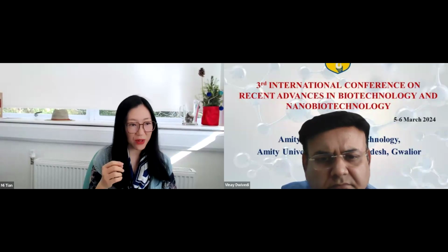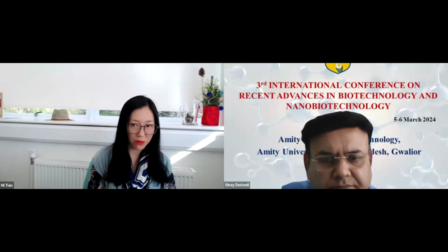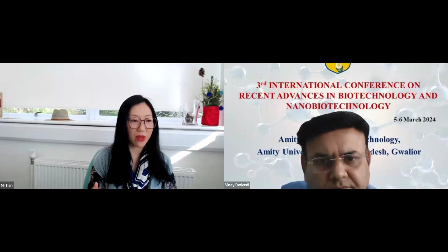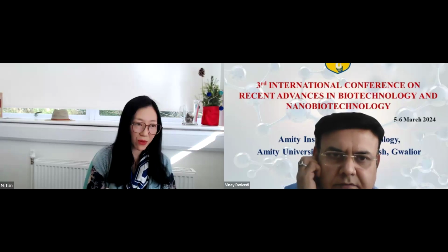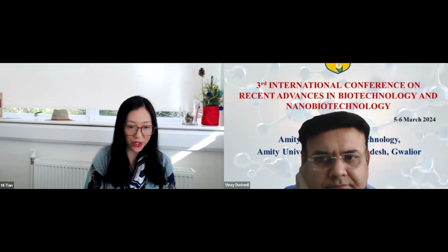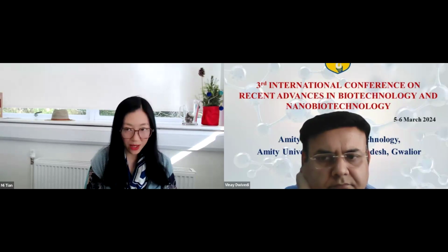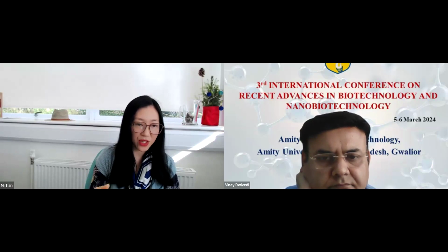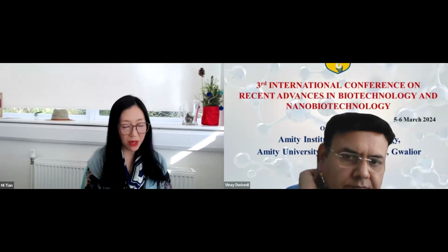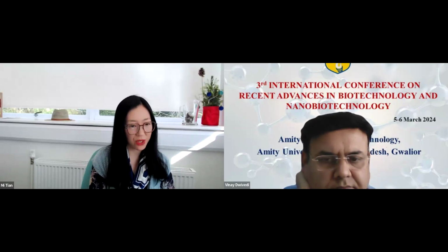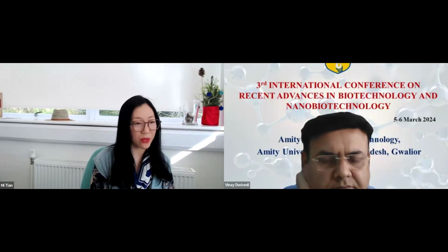Again, that depends on different materials. For the MOFs, for example, or most porous materials, we want to keep good crystallinity and reduce the size. The damage is to the porous structure, because some MOFs are not very stable. When you break them down, the porous structure collapses, which reduces the surface area. But sometimes bringing the particles down to nano size can generate active sites, which sometimes also benefits hydrogen storage. So it depends on the different storage mechanism and the different storage material.